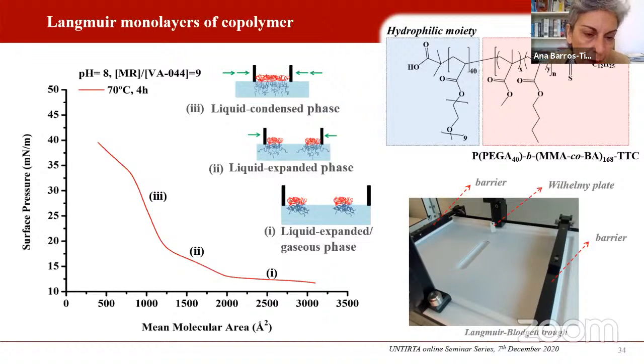So we carried out a parallel study, in this case using the Langmuir monolayers of copolymer, because we couldn't use the nanoparticles, as they would just disperse in water. They are aqueous colloids, so we couldn't really use the gold colloids. So we just used the copolymer spread at the water surface in a trough, as you can see in the bottom corner, and exposed this monolayer that forms at the air-water interface and can be organized by compressing the barrier, so reducing the area available to this monolayer.